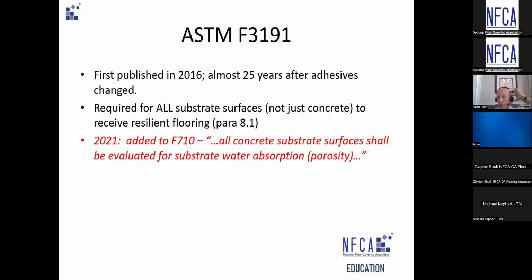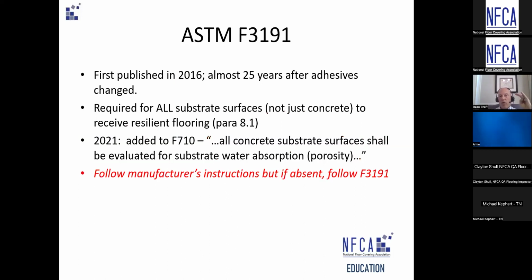So as far back as 2016, it was all substrates. It got bumped up with an F710 in 2021 as required there. And basically, long story short, it says do what the manufacturer tells you to do for porosity. Last I checked, Ultro says assume all concrete's non-porous. Nora, I think, said wait 2 minutes or 5 minutes, and I think maybe Forbo. Maybe Nora was 5 and Forbo was 2. But other than that, nobody defined what it was. So basically, the standard says do what the manufacturer tells you to do. If that manufacturer does not publish a way to do it, that's what the standard is.